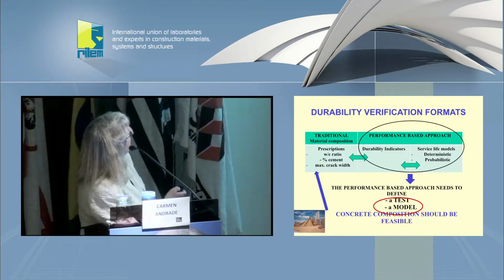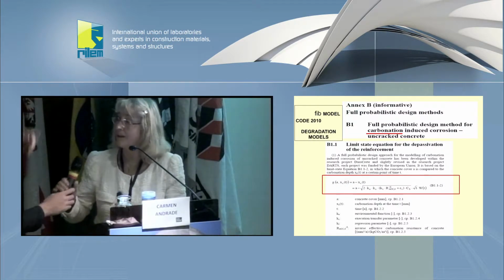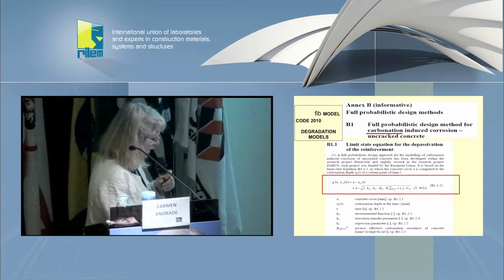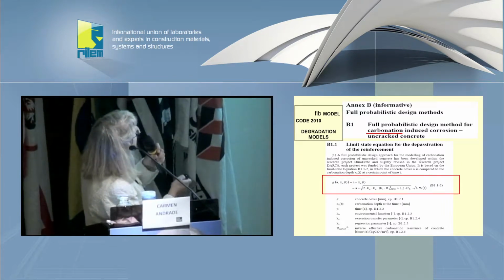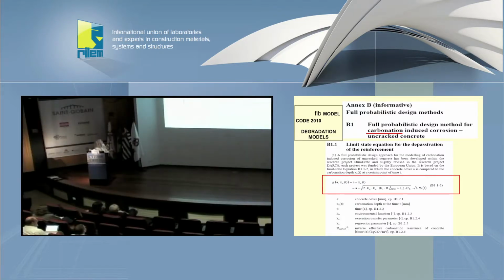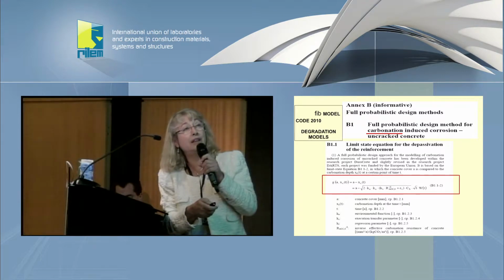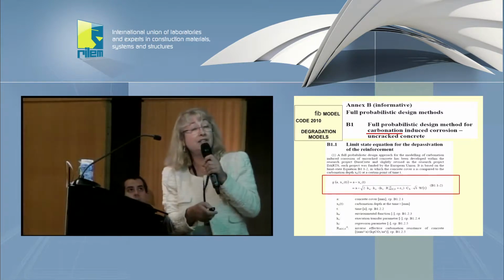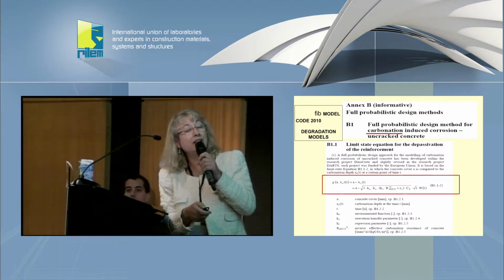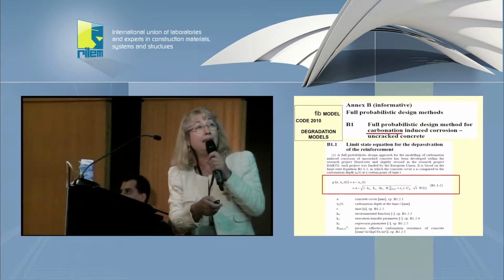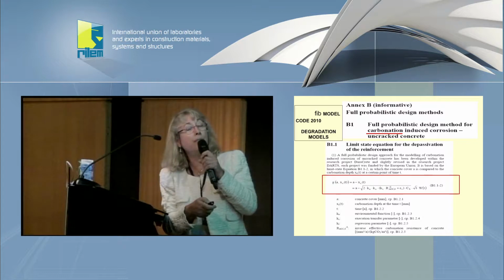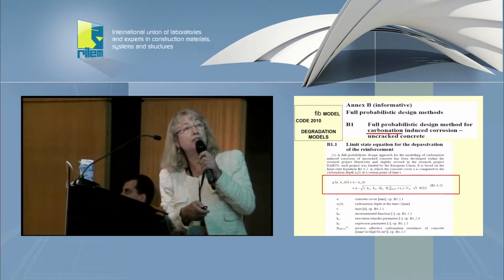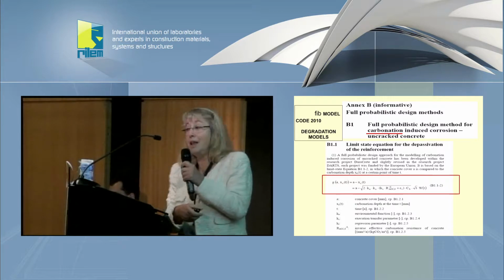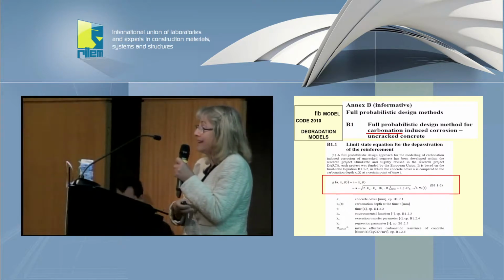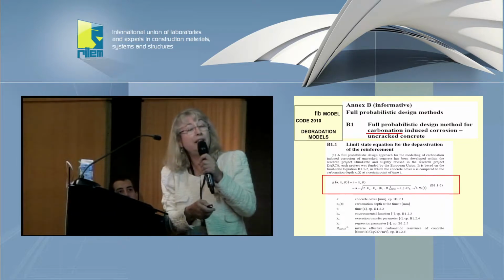About the Model Code, they are for the models. In the Model Code, we have a degradation or damage function for carbonation. This model I will not illustrate, only to say that it is too sophisticated, and this is one of the examples in which it shouldn't be taken strictly. The idea was conceptual when we developed this model, saying that the curing factor and the environmental factor should influence the performance, also the time of wetness, but when you try to give numbers, it's really complex to find the right numbers. In that case, this should be taken as conceptual.